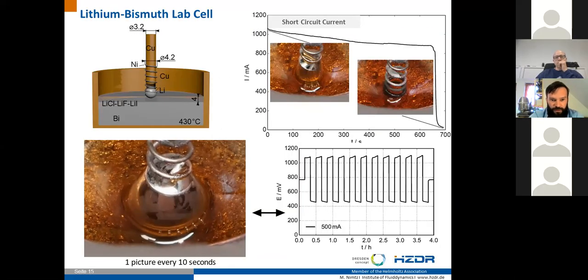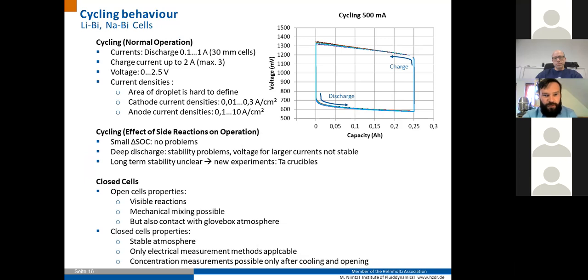Here we can see a resulting cycling diagram for these cells. The video here was made by taking a picture every 10 seconds, and you can see the cell was operated over several hours with quite large cycle times in between. And we also did some short circuit current tests, which means the current during discharge is as high as possible. You can see here the electrode is completely discharged into the bismuth, and this is a fully reversible process. Afterwards, it was possible to get the lithium droplet to stick to the nickel again.